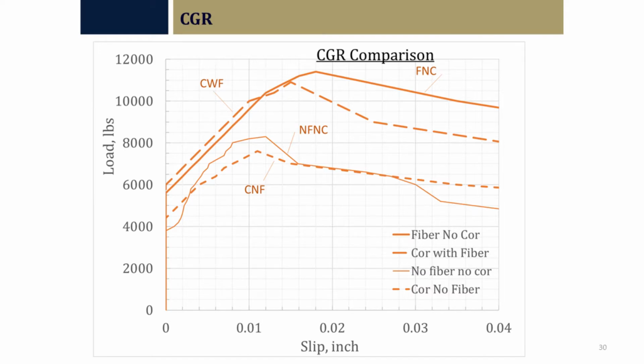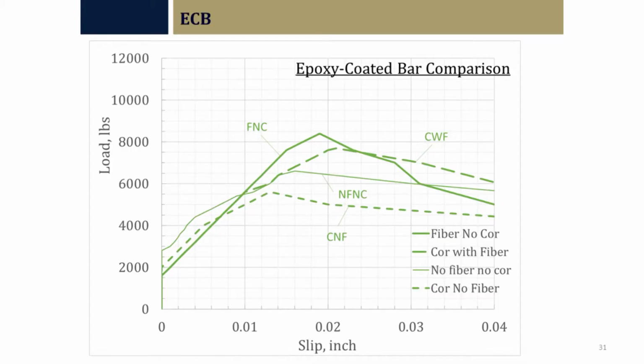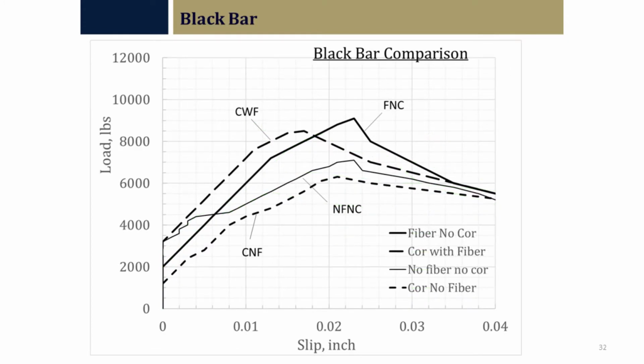So it's a pretty big difference between the peaks of these. The higher left and the higher up the chart, the better. So the fibers definitely increased. You look at that with epoxy, it's still sliding over to the right, but it is higher. It's certainly helped, no doubt about it. Uncoated as well. So you look at the three examples and you're showing that fibers do definitely help those as well.